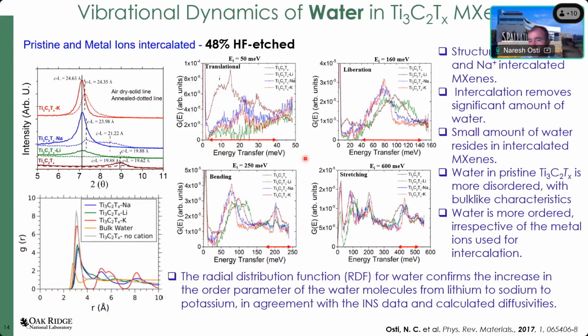Now, this first part was to look at the long-range translational mobility of the water. We also looked at the vibrational dynamics of the water using the inelastic neutron scattering technique. Here we use the same 48% hydrofluoric acid MXene, but we also look at the vibrational dynamics as a function of the type of metal ion intercalated between the MXene layers. I'm not going to go into detail, but what we found is that once you intercalate the metal ion between the MXene layers, there is a significant reduction in the intensity. This intensity is almost 3 times reduced. Even after that reduction, you can still see a huge difference in intensity.